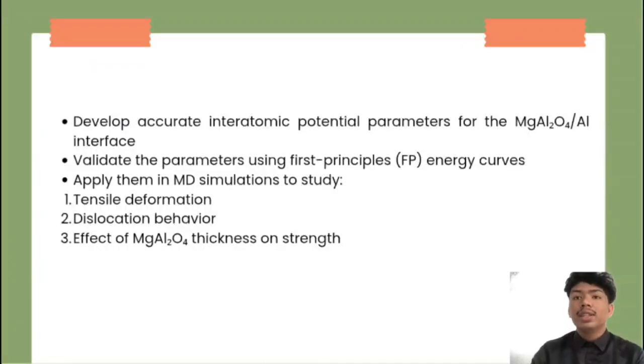This study aims to address key limitations in simulating the magnesium aluminate-aluminium interface, namely the absence of validated interatomic potential models. The primary objective is to develop a set of accurate, efficient, and practical potential parameters that can be used in large-scale molecular dynamics simulations. To achieve this, the first goal is to generate new interatomic potentials for aluminium-oxygen, aluminium-magnesium and aluminium-aluminium interactions. These are derived by fitting classical potential functions, specifically the Morse and Buckingham models, to high accuracy energy curves calculated from first principle methods.